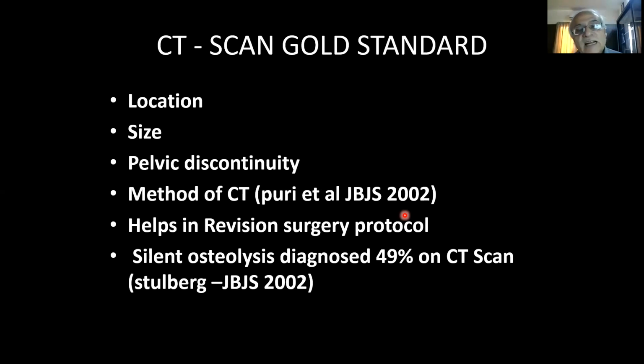And this is great work by Stulberg. First time he reported silent osteolysis. All patients who were operated on after 10 years or so, he did a CT scan of all the patients, and he saw there were no symptoms. And the silent osteolysis was 49%.